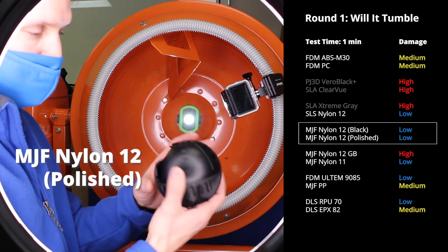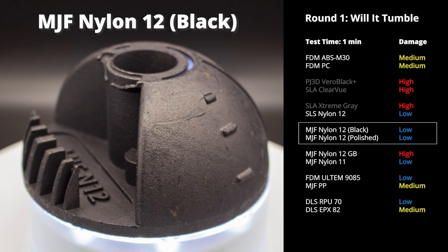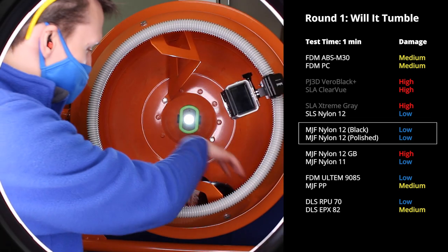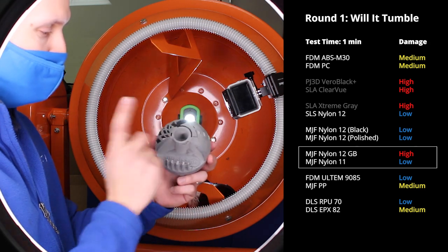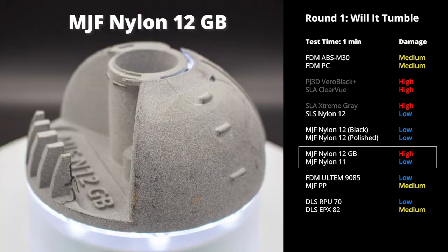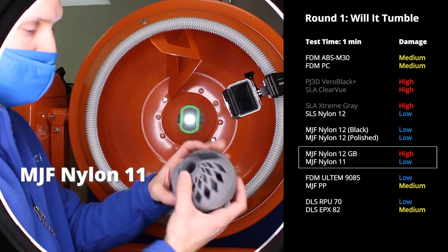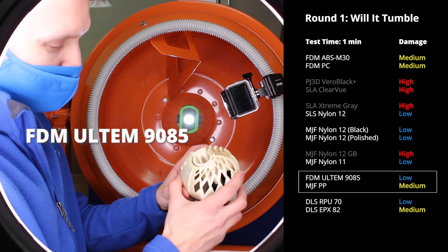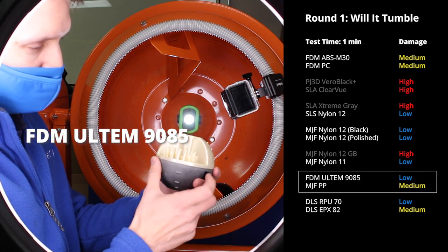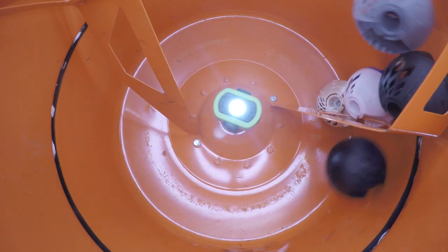Multi Jet Fusion is holding up pretty well. The polished piece and the regular Nylon 12 — so far, so good, doing great. The glass bead is actually a little bit chippy, and I'm thinking I may consolidate the Nylon 11 with our SLS nylon. Ultem, our high performance FDM, is living it — it actually looks pretty good, relatively untouched. It is a tough material.